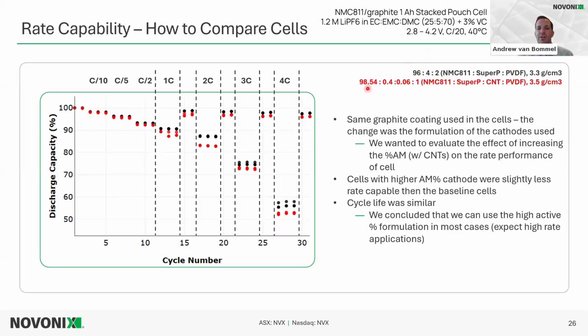So in this way, we would expect this cell to have higher energy density. So this is going from 96 to 98.5 NMC, 0.4 Super P. There's some CNTs in there and a little less PVDF, half the amount of PVDF. It is calendared to a little higher amount, but this ends up being approximately the same porosity as the initial one because we're losing some of that lower density inactive materials. So again, the same graphite coating was used for both these cells, the red and the black.